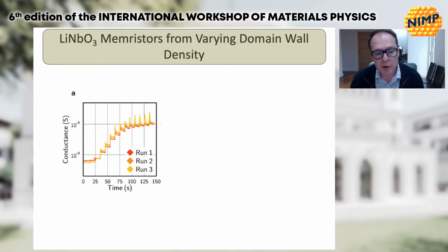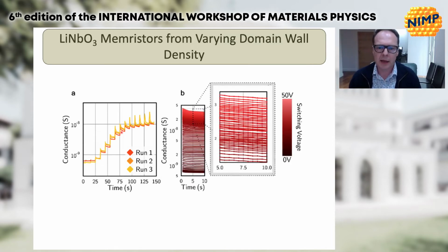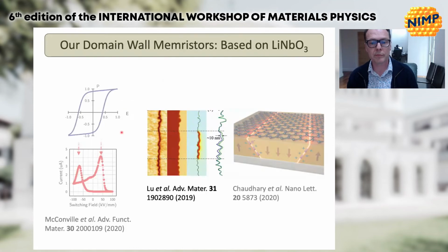So we've changed the microstructure progressively by hitting it with higher and higher voltages. And at each increase in voltage, you generate more reverse domains or larger domain wall densities. And so you get a different resultant conducting state. And you can do this at relatively fine levels of control and really get quite large numbers of states associated with these rather simple memristors. Okay, that was the simple-minded thing that we did in Belfast.